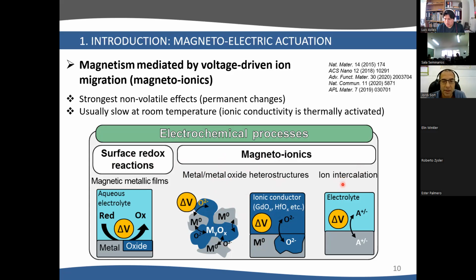Another mechanism exploited in some of these papers is ion intercalation. So if people, for example, use iron oxide, they immerse this in a lithium electrolyte, typical from batteries, and then the lithium can be incorporated in the iron oxide when you apply voltage. And this changes the magnetic properties of the iron oxide. So this magnetoionics causes non-volatile effects or permanent changes.